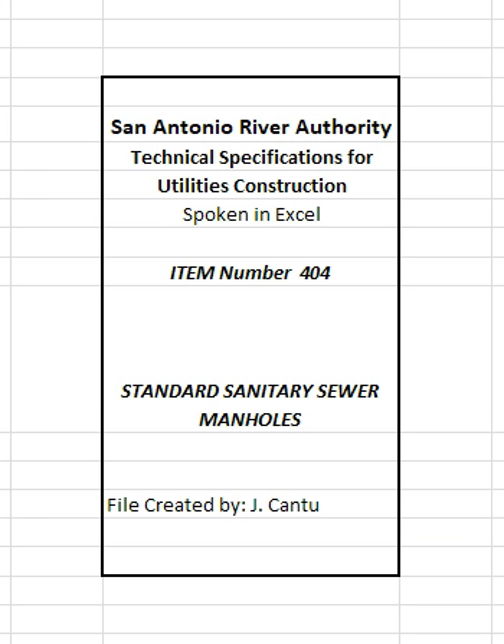If the manhole fails the test, identify the leaking areas by removing the head assembly, coating the interior surfaces of the manhole with a soap and water solution, and repeating the vacuum test for approximately 30 seconds. Leaking areas will have soapy bubbles. Once the leaks have been identified, complete all necessary repairs and repeat test procedures until satisfactory results are obtained.